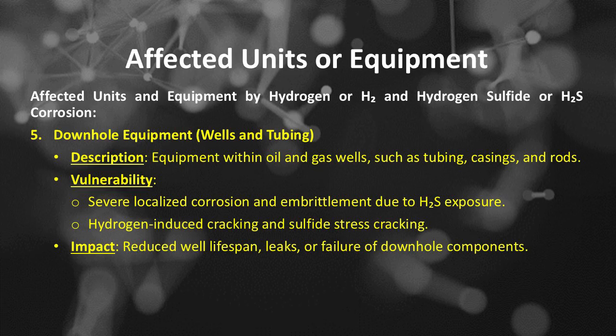The vulnerability of high-temperature hydrogen (H2) and hydrogen sulfide (H2S) corrosion to the downhole equipment, wells and tubing includes severe localized corrosion and embrittlement due to H2S exposure, hydrogen-induced cracking and sulfide stress cracking. The impact to the downhole equipment, wells and tubing: reduced well lifespan, leaks, or failure of downhole components.